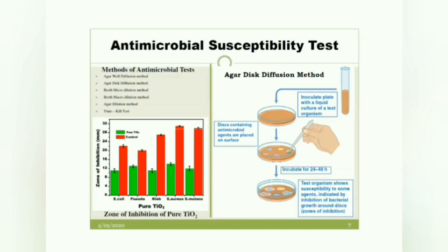Based on this, we have used the agar disc diffusion methodology. We have taken a Petri plate where the culture medium is, nearly 25 ml per plate. Then we have taken the discs, and these discs are just placed over this where your test part should be, and it is incubated for nearly 24 to 48 hours. After this, we can see there will be a zone of inhibition, which means it is going to prevent the bacterial growth.